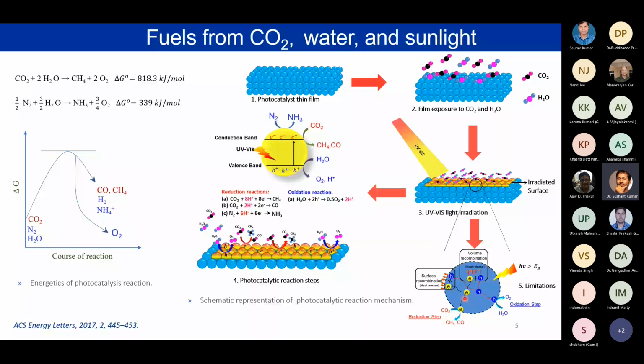Now, besides those thermodynamic aspects, there is also a kinetic aspect, because these reactions are very sluggish, and because of a lot of hindrances, the product that we are getting right now is not very high. It has both of those limitations I told you about, the reactor design as well as the kinetics. And it's a global issue that is prevalent. But the good point is that these reactions are feasible, and one can really convert the CO2 in the presence of sunlight to some fuel which can be used.